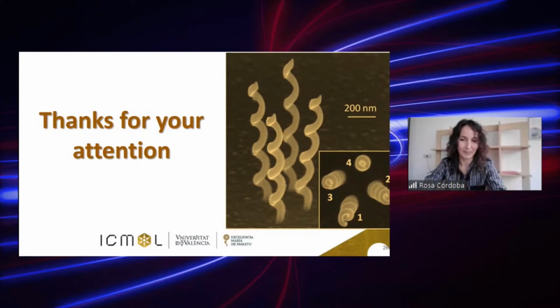Yes, it is clear that they were made in a vertical way, and to put them in plane to do the electrical characterization, I was using a nanomanipulator that is mainly used, for example, for the lift-off of TEM lamella preparation. So I just pushed there and tried to put them in plane using this nanomanipulator. And later on, I made the supporting electrical contacts, also using platinum based on focused-ion-beam-induced deposition.